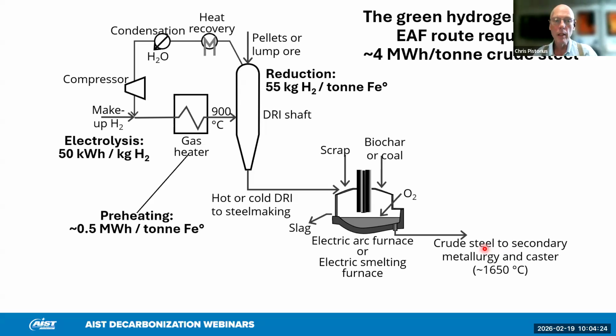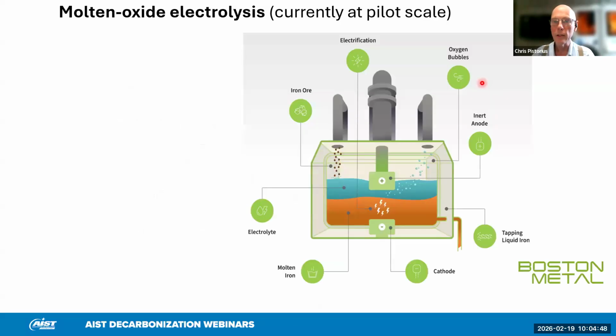And then a substantial electricity requirement is to preheat the gas, because this is how we get the energy for the reduction reactions and to heat up the product. And then we need the normal steelmaking number. So if you add all of these together, they are close to 4 megawatt hours per ton of crude steel. So that's a combination of existing processes about to be industrialized, so very high on the technological readiness level.